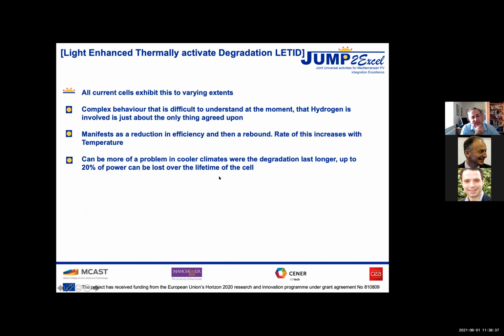So this is an even more intriguing effect. Again, more or less all current cells, even multicrystalline cells in silicon, show this degradation to some effect. It shows complex behavior. It's difficult to understand at the moment. The only thing that many people working in the field agree on is that some hydrogen is involved somewhere. And this is through some rather clever experiments that introduce hydrogen and deuterium, alternative hydrogens, and look at the behavior under degradation. So we're pretty sure hydrogen's involved, but we don't know exactly how.